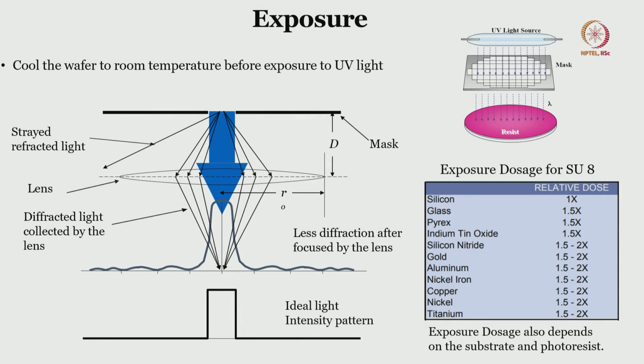When you expose the photoresist, the UV light passes through the lens, and you can see the ideal light intensity here. However, the diffracted light collected by the lens is shown in this particular case, and there is less diffraction after focusing by the lens. So, we get this kind of pattern when we expose the photoresist by UV light through the photolithography system.